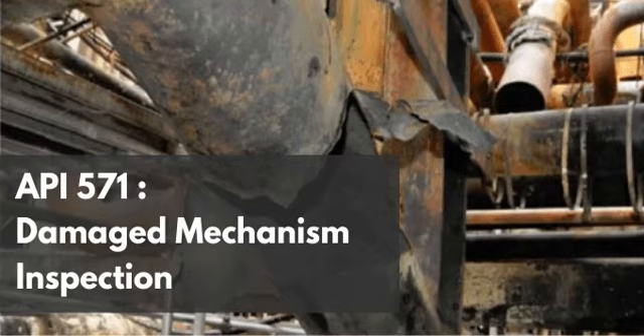Okay, break that down for me. What do you mean by passive armor? So under standard sour operational conditions, carbon steel and low alloy steels aren't completely defenseless. They react with the environment to form these microscopic protective surface films. Like an oxide layer. Similar, yeah. Specifically, they form iron carbonate, iron sulfide, or complex iron oxides. And these films normally passivate the steel surface. They significantly slow down any further corrosion. Right, the steel basically protects itself.